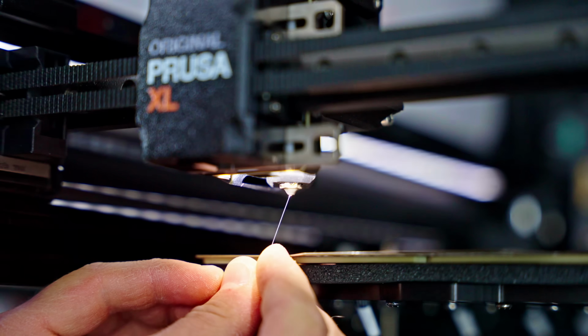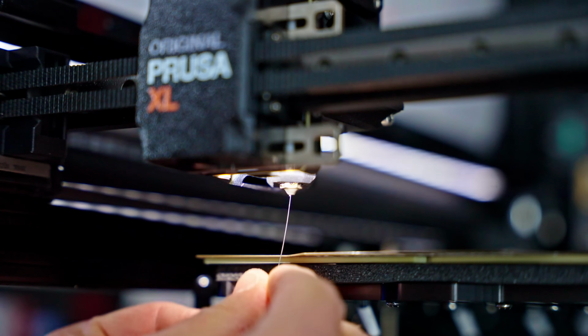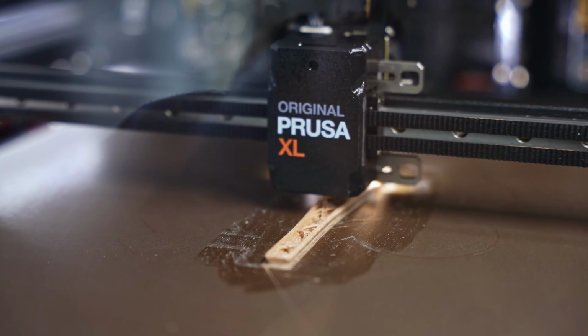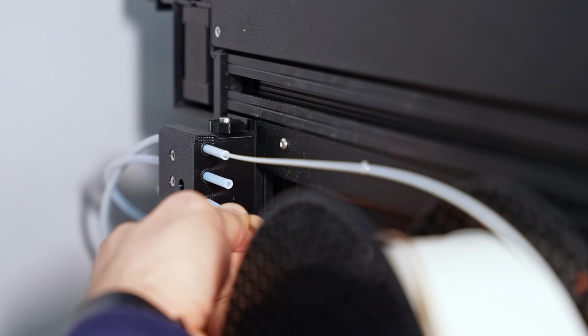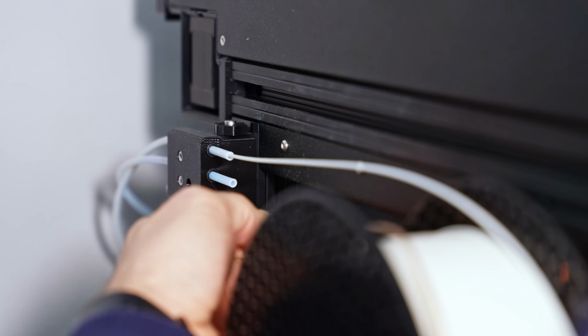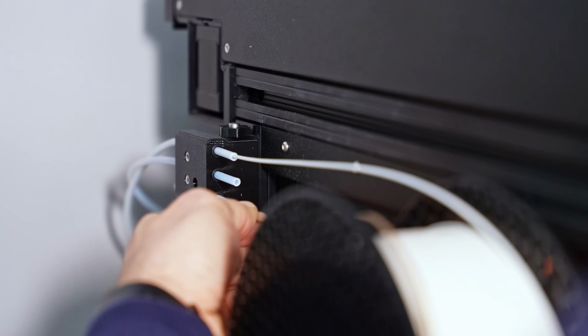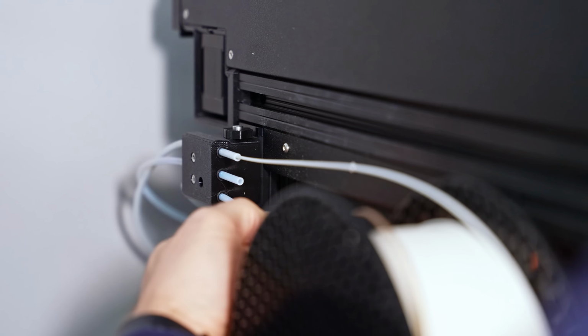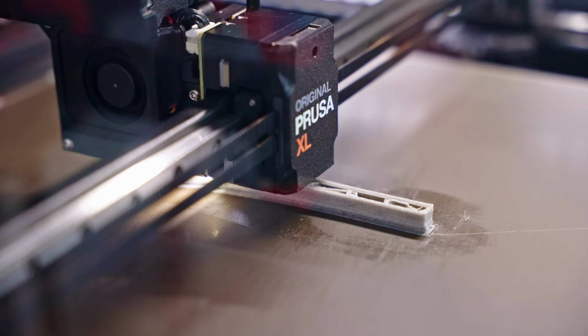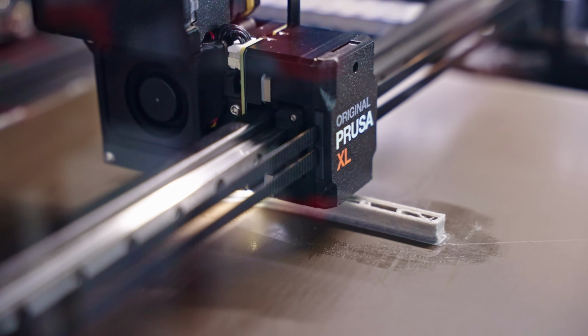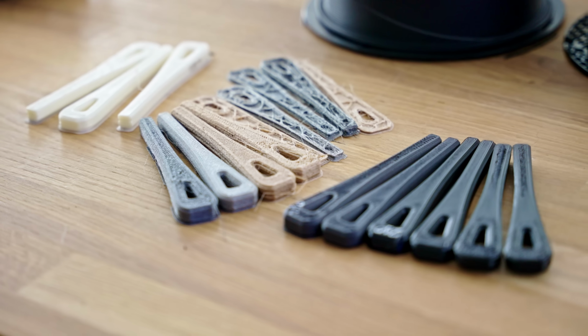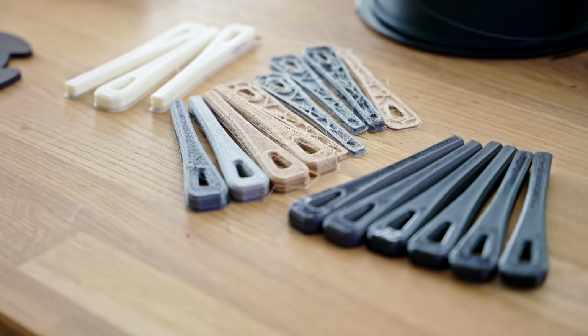Because I had loaded the printer with a 0.8mm E3D nozzle X, clogging wasn't an issue there, and I could get around to the extruder feed issues by just pushing the filament in by hand and keeping a light pressure on it the entire print. These parts only take about 12 minutes to print, so I can just do that by hand. Overall, these filaments all printed pretty much like the standard PC blend.